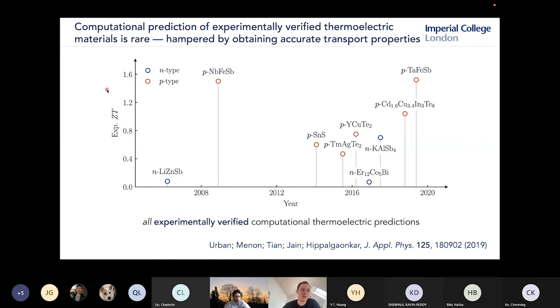Now, for a thermoelectric material to be viable, we really need ZTs above 2 and ideally beyond 3. And you can see that basically across all of these materials, the best ZT we were able to achieve was about 1.6. So we're well below what we really need. And in a thermoelectric module, you need both P and N-type components. And if you look at the N-type materials that we found in blue, these are really poor performing. They only get ZTs of about 0.8. So we have a lot of work still to do.